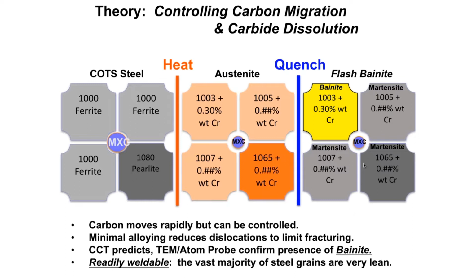What we did with our process is we chose a different path, and we actually heat up in just a few seconds. We allow carbon migration to just start to occur. So for example, the 0.80 or 1080 pearlite drops down to 0.65 carbon. The other three areas might have 0.07, 0.05, or 0.03 carbon, for example. And as the chromium carbide sluggishly dissolves, we end up with 0.3 carbon in some regions.